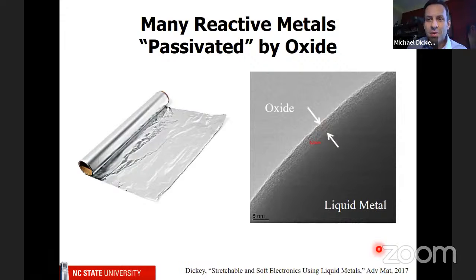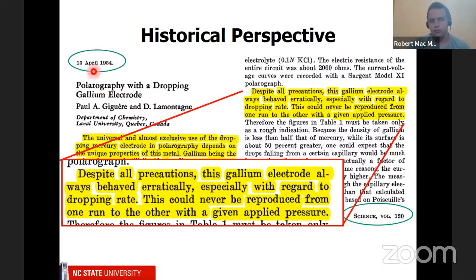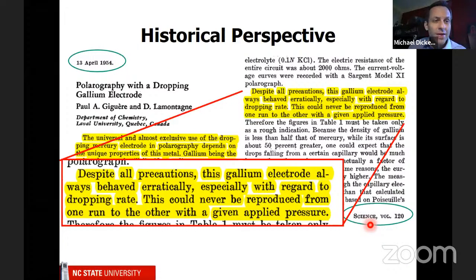And this is not new. In fact, this is a paper from 1954, and it was published in Science, believe it or not. What these authors were trying to do was a technique called polarography. This is where you take a needle and you pump liquid metal out, and you use that as an electrode for electrochemistry. And what they found, they said, despite all precautions, this gallium electrode always behaved erratically. So that means it doesn't behave consistently, especially with regard to dropping rate, so how often they pump it out and it drops and drops and drops. It says this could never be reproduced from one run to the other for a given applied pressure.